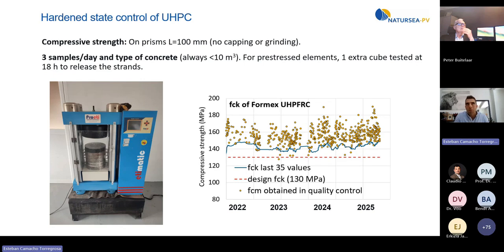Normally, rarely do we produce more than 10 cubic meters per day, but we produce 3 samples per day and type of concrete. If we modify the fiber content or we are developing concretes for 2 different projects, we do 6 or 9 or whatever is required. Sometimes we also produce an extra cube because when we need to release the strand of pre-stressed beams or elements, we need to test at 18 hours.